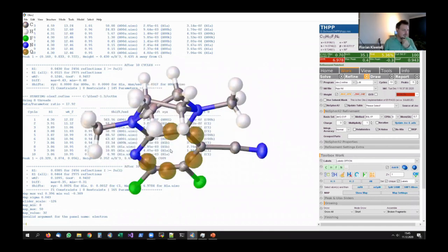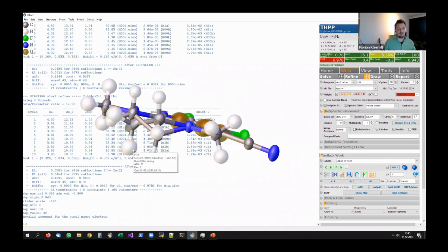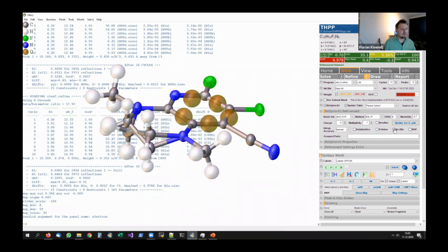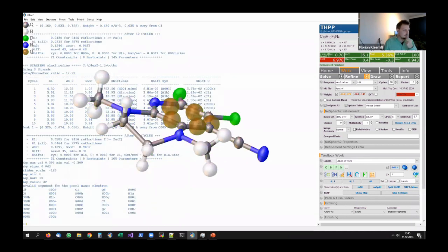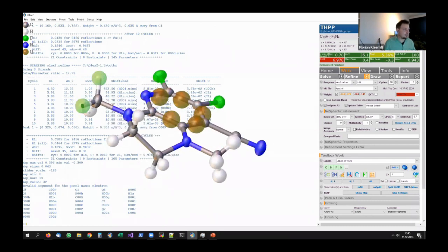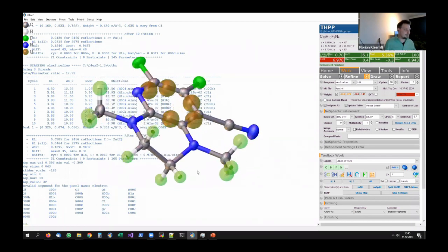So what we need to do is we should keep those atoms with restraints in our disorder component or constraints while some of them we can refine freely. So what I'm going to do is I'm going to remove the auto features which would make my hydrogen atoms anisotropic and remove any affixes, and I will manually select this component as the major component. So I will now select all the hydrogen atoms. I can do that by clicking, or I type sel $H down here on the terminal, which will select me all hydrogen atoms. I will type anis -H, because usually anis would just make the non-hydrogen atoms anisotropic, which is very fine for independent atom model refinements, but we are using Hirshfeld atom refinement. We can refine these freely.